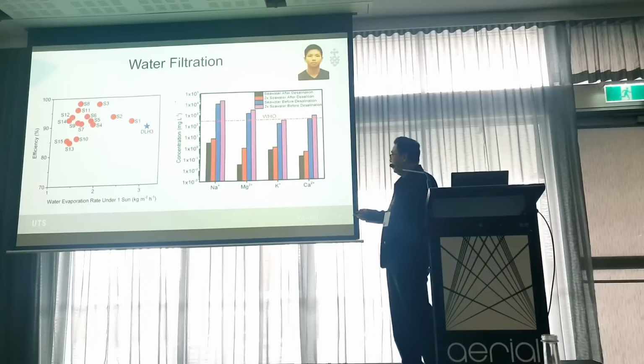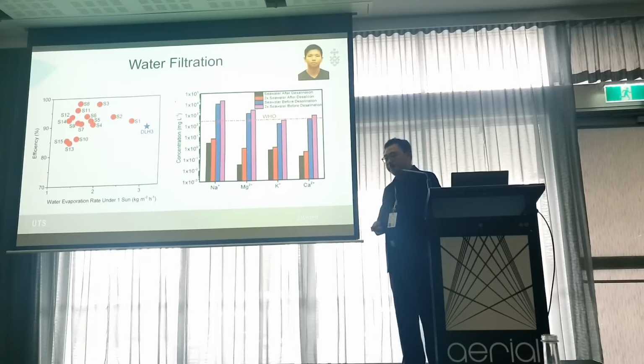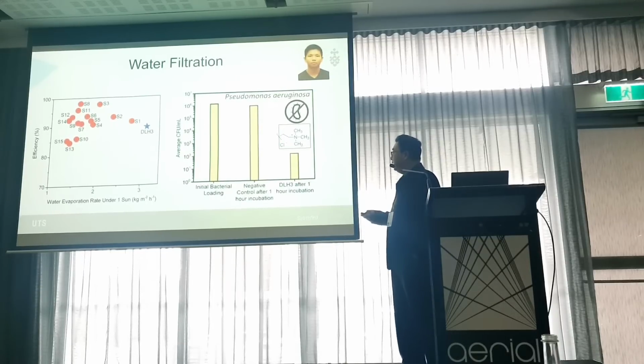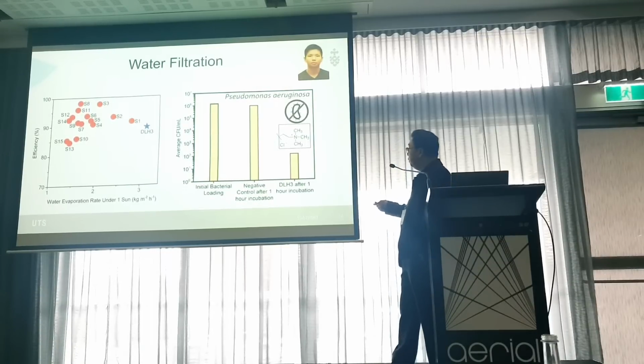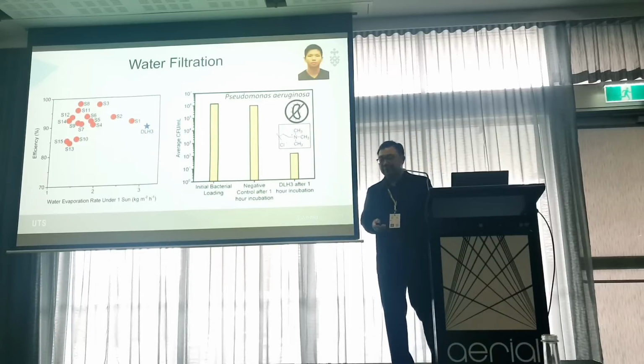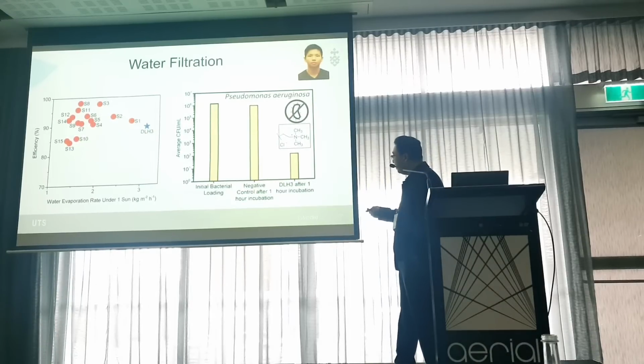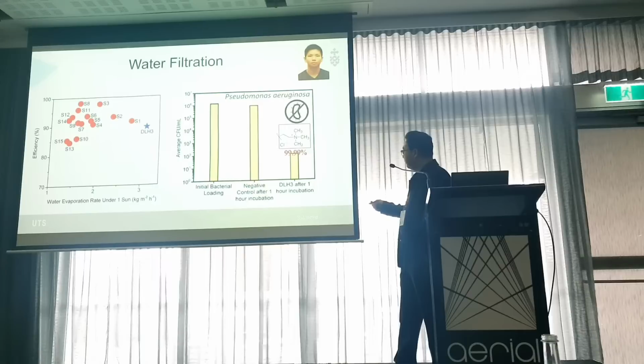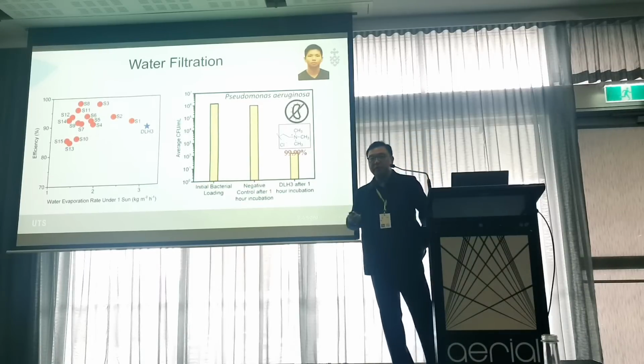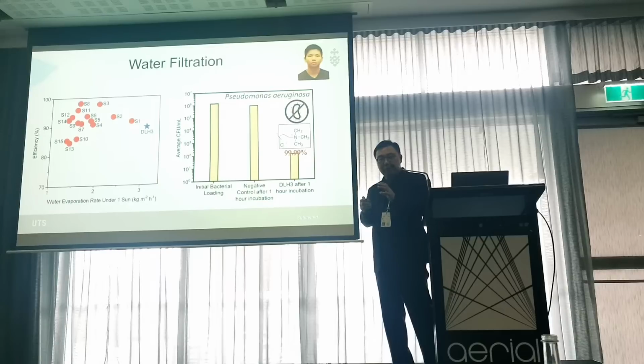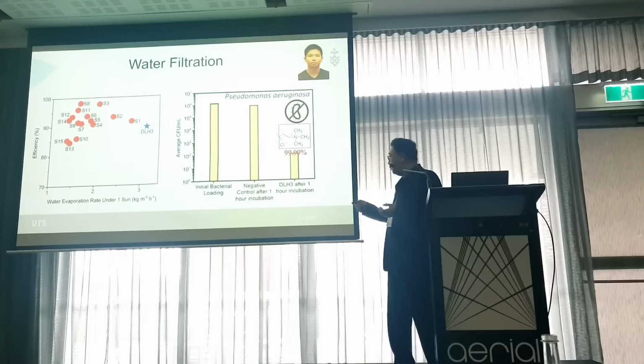As you can see, in this case, the water obtained through the hydrogel system has a very low salt concentration. Additionally, due to the introduction of these positively charged functional groups, our hydrogels also show good antimicrobial property. We can kill 99.99% of the bacteria. To achieve the same effect, conventional studies usually introduce several nanoparticles or use carbon quantum dots, but both of them are expensive. We only need to tune the structure of the polymers to achieve this ability.